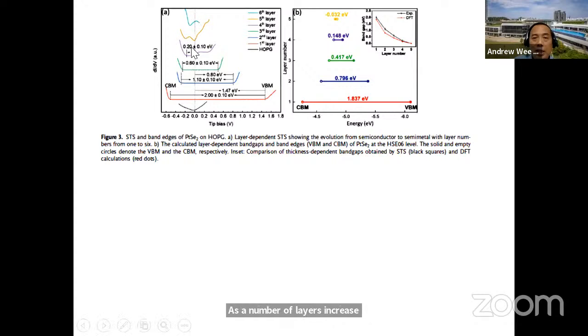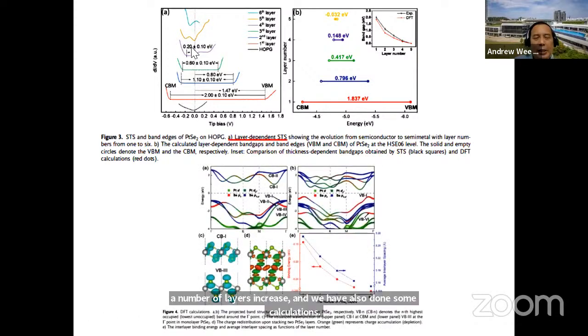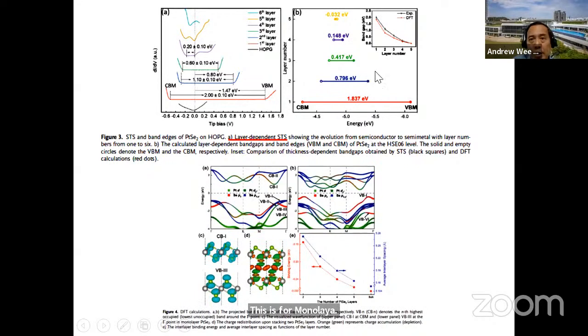And we have also done some calculations. These calculations, which have also been done by others, this is for monolayer, this is for bilayer, and you notice the band gap is decreasing. You see in this plot that the theoretical DFT calculated band gap and the experimental band gap that we measured are quite similar. So it is possible to change the band gap of this material. You can make devices with whatever band gap you want if you're able to control the thickness of the material. That's why PtSe2 is so interesting.